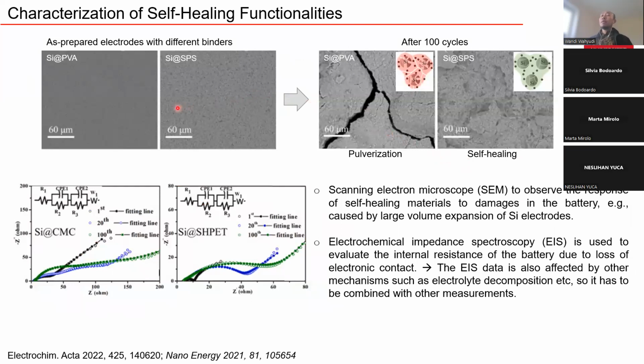One example is presented by the authors in this literature. They use PVA binders for some silicon electrodes and SPS binders for other silicon electrodes, and they cycle the cells for 100 cycles. They showed that the silicon electrodes with PVA binders show a lot of cracks, while the other electrodes show that the electrodes can maintain the smooth surface.